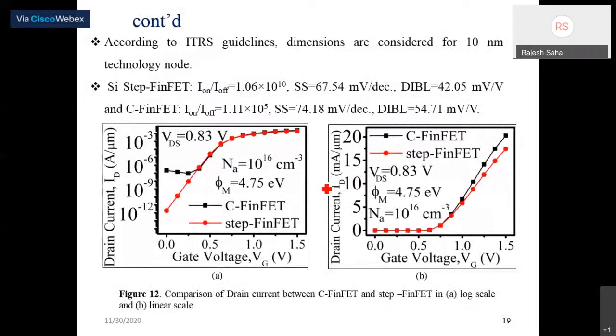Next is the comparative study of the step FinFET, where we have taken, as I told, the ITRS requirement. This red color is the step FinFET in terms of transfer characteristics, and this black color represents the conventional FinFET. This is the linear scale and this is the log scale. As you can see, there is significant improvement in the off current for the step FinFET due to better gate control. The on current also reduces, but not by that significant an amount. The on-to-off ratio we got is in the order of 10^10.